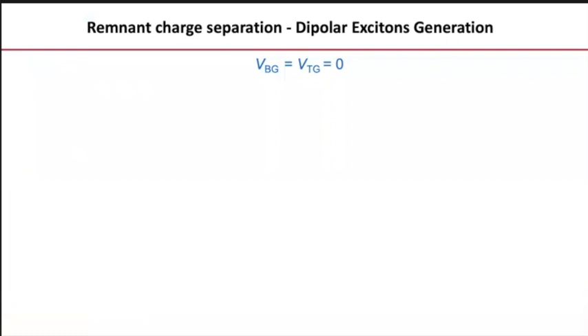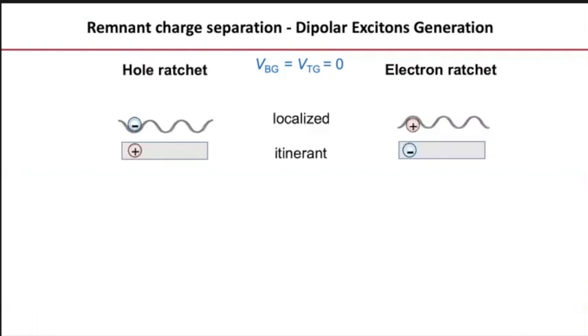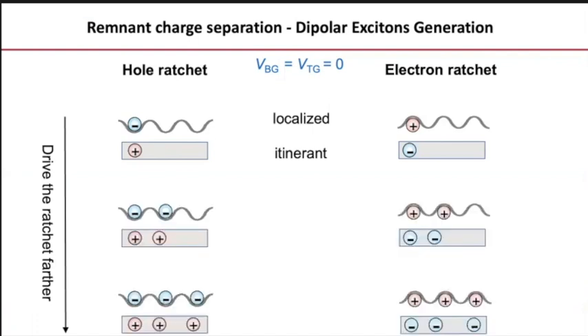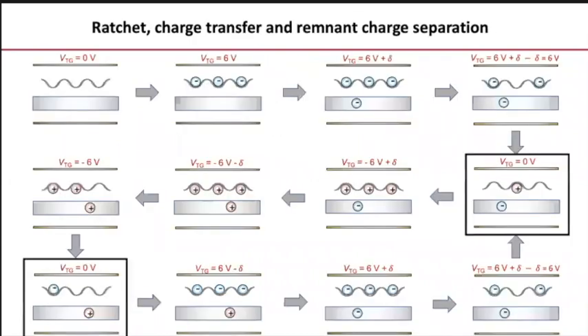Let me show you something which is perhaps even odder. If we now go all the way back to charge neutrality, what we see in the system is that there is a remnant charge separation. We generate dipolar excitons, such that the system, whether it's in the hole ratchet or an electron ratchet, becomes like that. And in fact, we can drive the ratchet further, and going back to neutrality and zero displacement field, we're left with a system where we have a number of electron hole pairs, which we can vary at will.